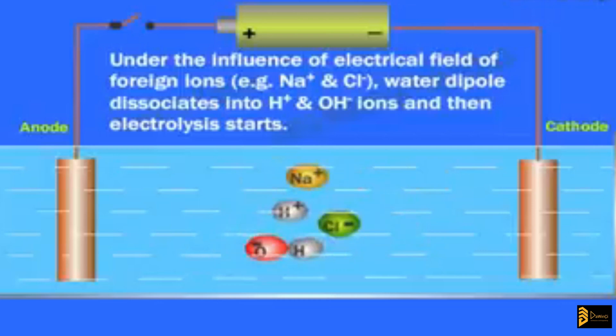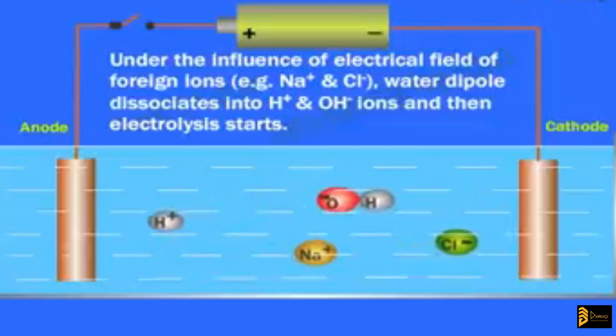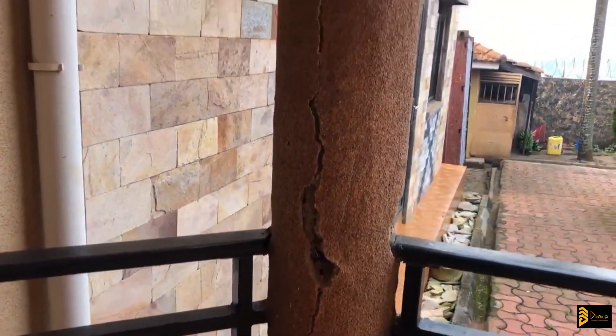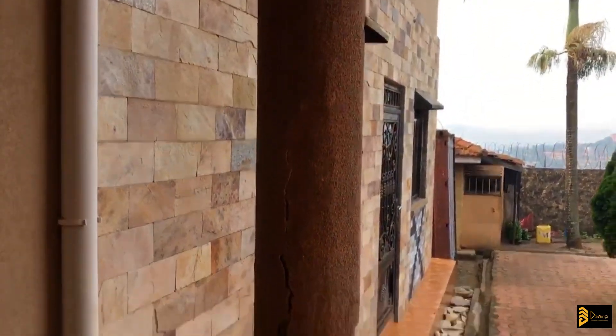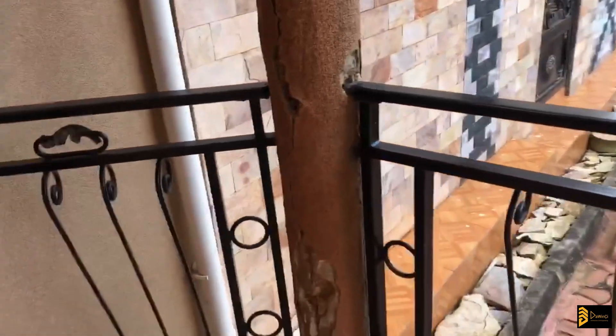Now that is exactly what happened in this scenario. It should have been okay for an aluminium piece to be hooked with a steel bar — but in this case, it is on an external column that is exposed to rain and humid conditions. When it rains over a period of time and the column gets wet and absorbs water, that water starts acting as an electrolyte. Then we have aluminium and we have steel.